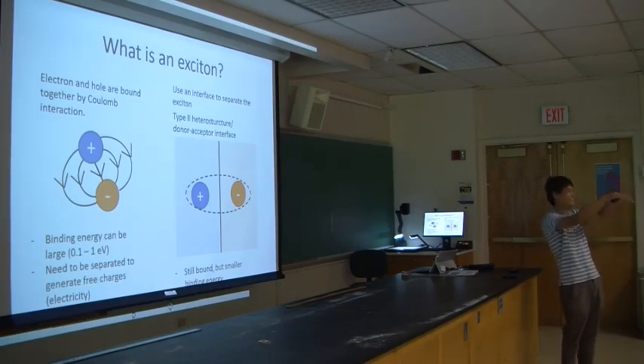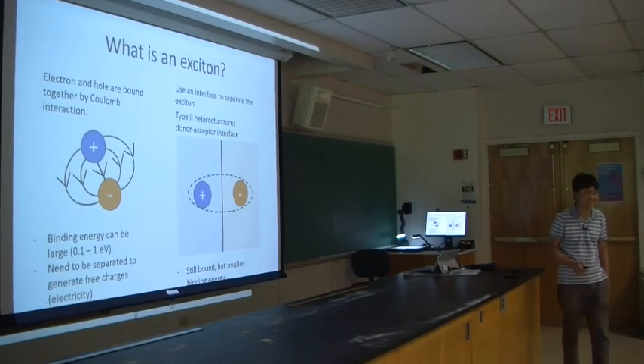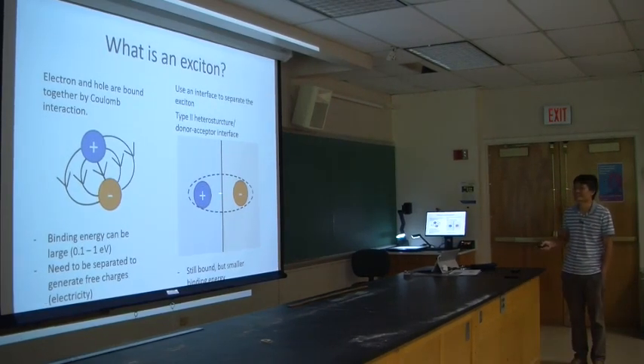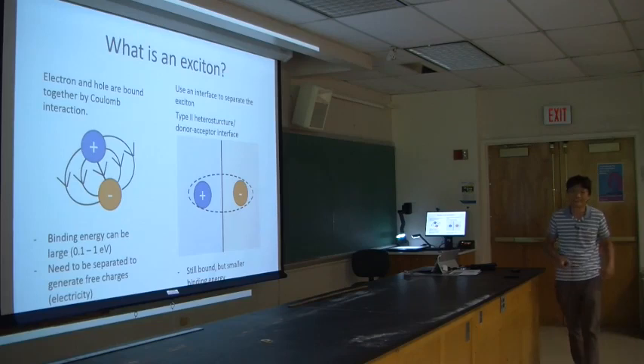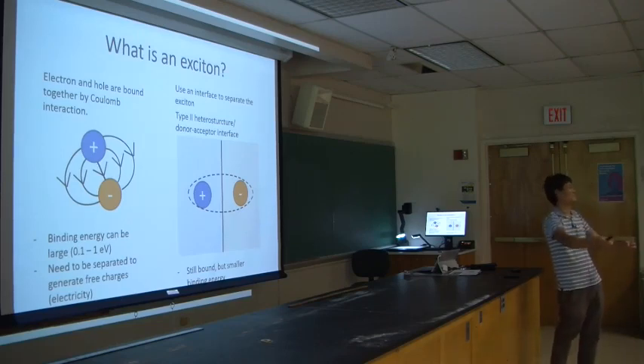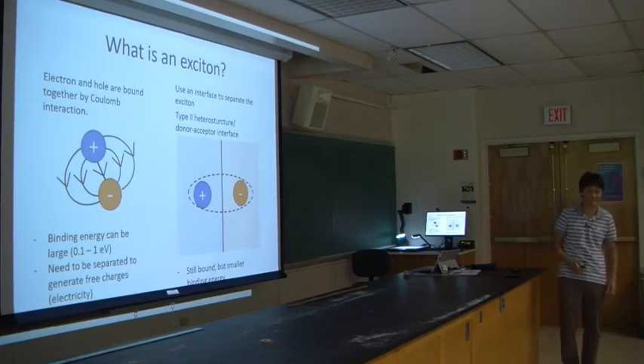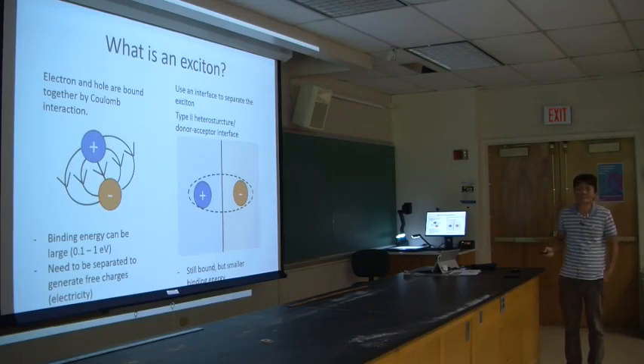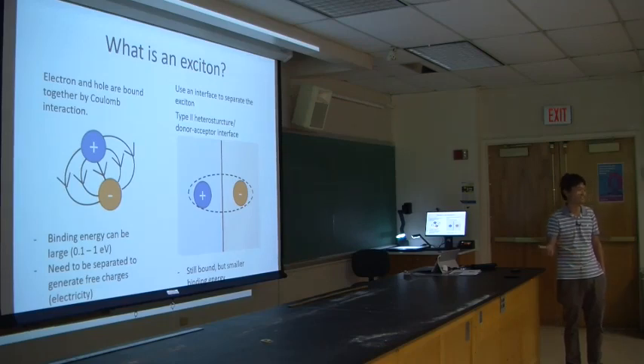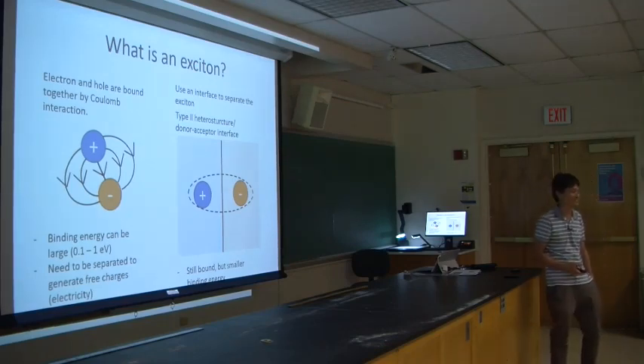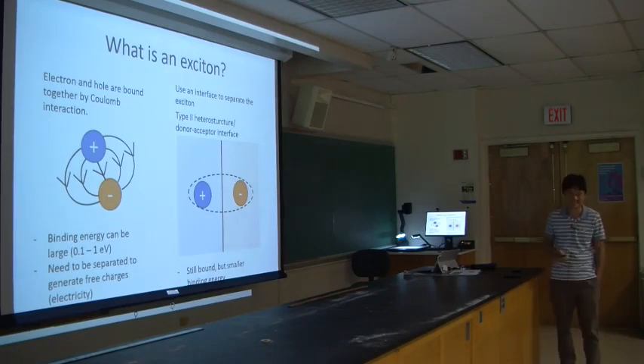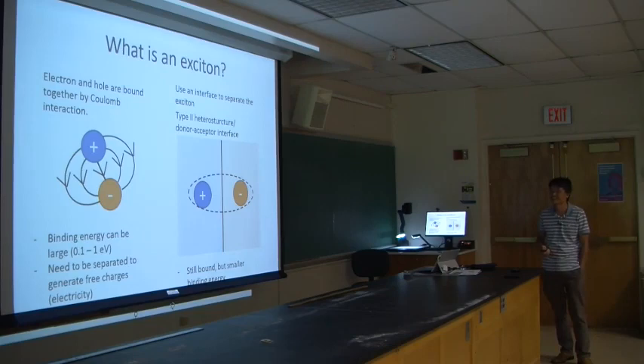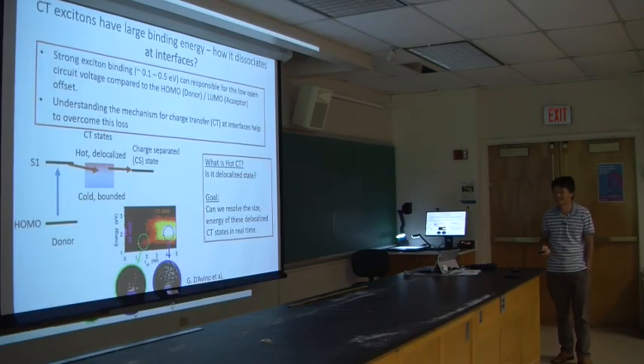What happens is you have an energy offset at the material's interface. So in these cases, electron transfers from one side to the other, and hole transfers to the other side. Now you have so-called charge transfer excitons, because it involves a charge transfer process to make these excitons. These are easier to dissociate, but they are still bound. Usually they still have hundreds of milli eV of binding energy. So how do we separate this kind of CT exciton at the interface? That's one of the scientific questions we are looking at.